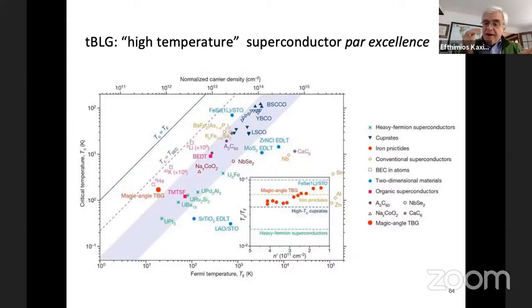However, if you scale that temperature by the Fermi temperature, essentially by the velocity of the electrons, which is the more meaningful comparison to give you a sense of how strongly correlated the system is. So if you scale the temperature, this is the ratio of critical temperature over the Fermi temperature. The red dots are the values for the magic angle twisted bilayer graphene. This dashed line is the high TC cuprates. This dashed line is the iron pnictides, and this is the iron selenide. These are all considered very high temperature superconductors. In this scaled temperature, the graphene is very high, which means that these correlations are very strong already.